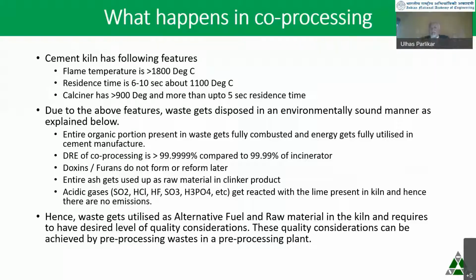So if you look at this particular process of co-processing happening in the cement kiln, there's absolutely no cause of concern on the emission. And this is not a statement that I'm just making. There were several demonstrations which were done, and I was a party to that, and nothing could be found which was abnormal or atrocious from the emission considerations point of view.